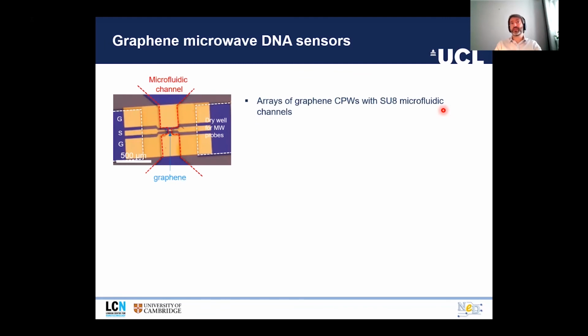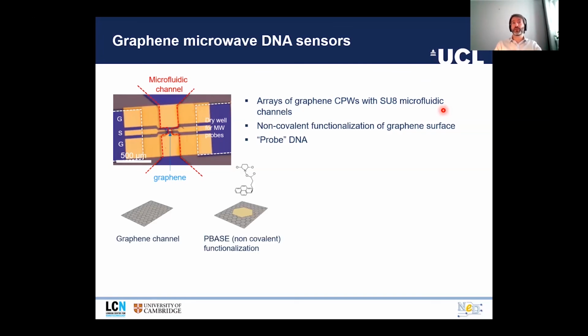The first material that we are investigating is DNA, because DNA really allows us a very good control. So from an engineering point of view, it's a wonderful biological material. And so we functionalize the graphene surface using P-base, which allows non-covalent functionalization. That's the very typical procedure used in many graphene-based biosensors. Then we immobilize a sequence of DNA. It's a complementary sequence of the sequence we would like to detect.